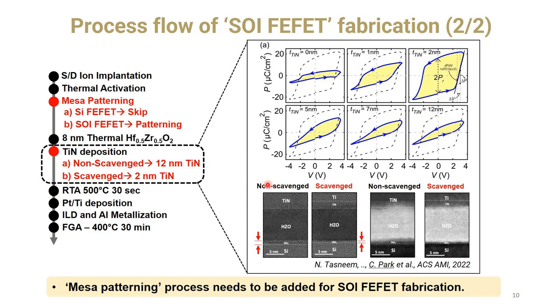And we did a TEM analysis, and we found that in this 2 nanometer device, the IL layer is thinner. So we call it scavenged. The IL is scavenged in this device. So TiN 2 nanometer is very effective in scavenging the IL. That's why we chose TiN 2 nanometer as the scavenging device and 12 nanometer TiN as the non-scavenging device.